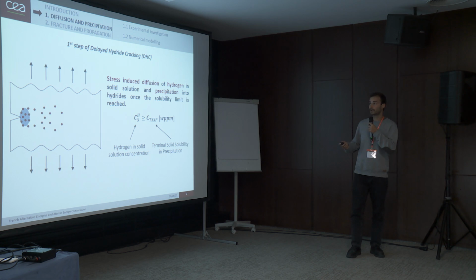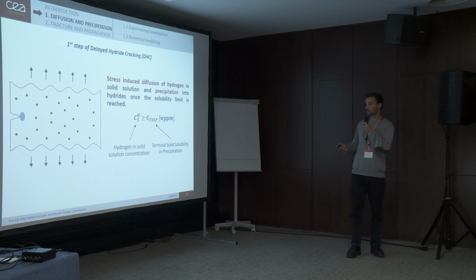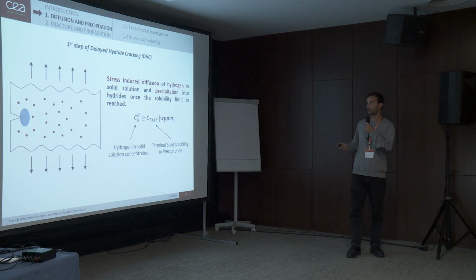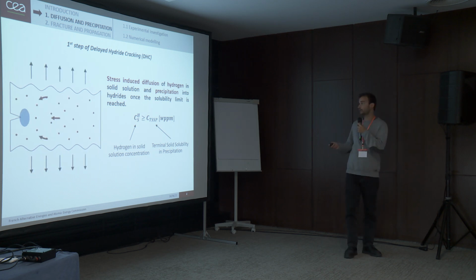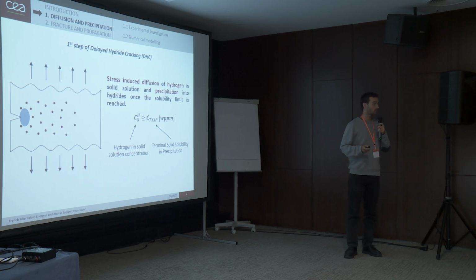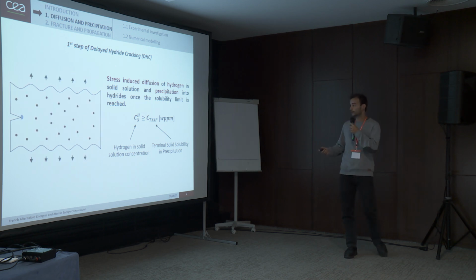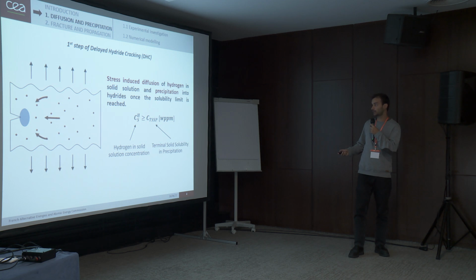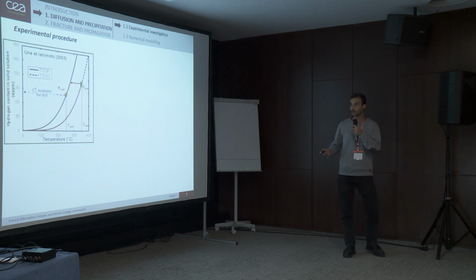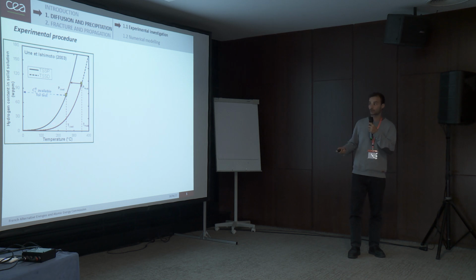It can be divided into two steps. The first step is the stress-induced diffusion of hydrogen in solid solution, towards the notch tip, and the precipitation into hydrides once the solubility limit is reached. This solubility limit is called terminal solid solubility in precipitation, because as you can see on this figure, showing the hydrogen content in solid solution as a function of temperature, the terminal solubility, the limit of solubility, in dissolution and in precipitation is different.